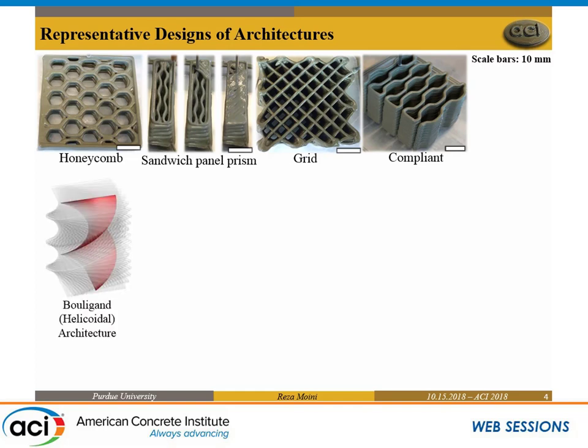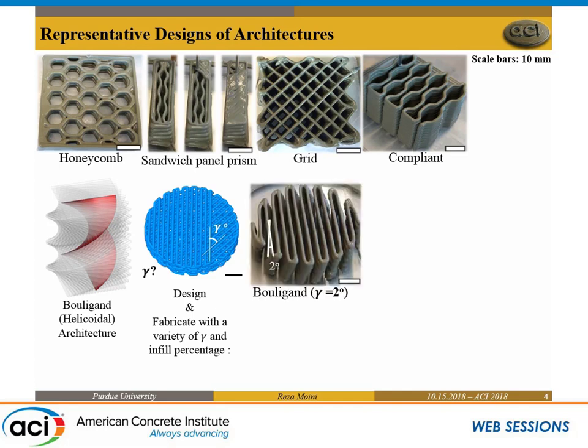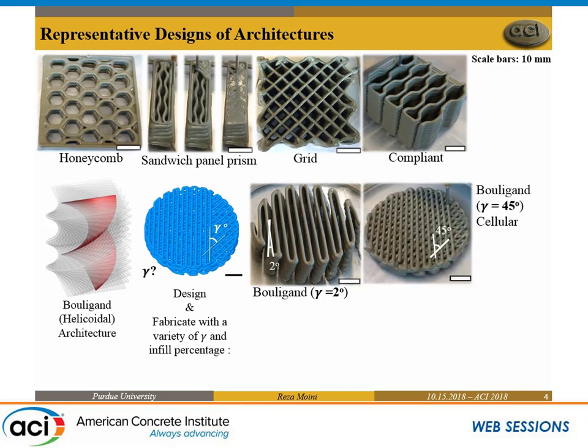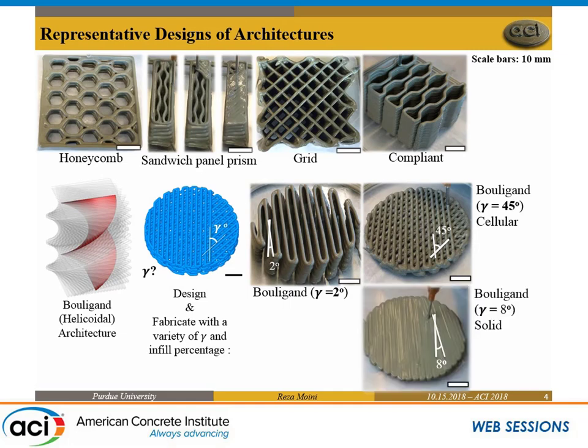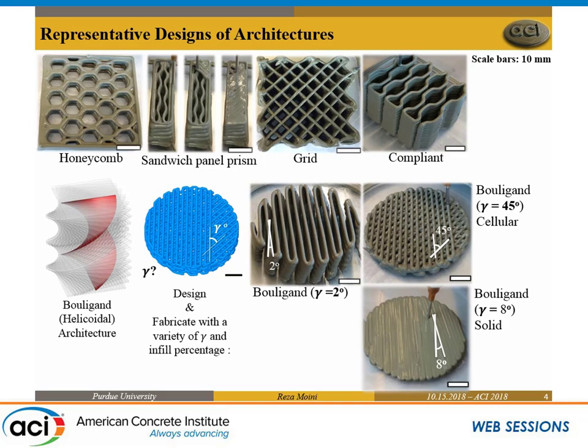We call every rotation between layers the pitch angle. So if you print a 2-degree pitch angle — rotating 2 degrees as you build up — you get one structure. If you print 45 degrees, you get another. You can also play with infill percentage: going from 60% infill to 100% infill gives you a solid element. I want you to keep in mind the compliant architecture on the top right — what happens when we actually test this?